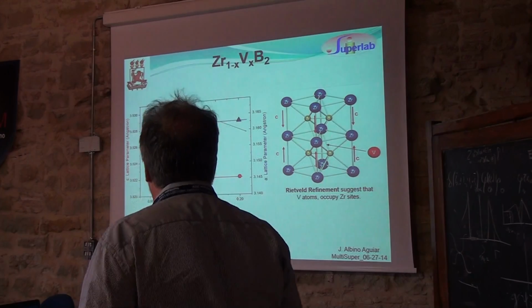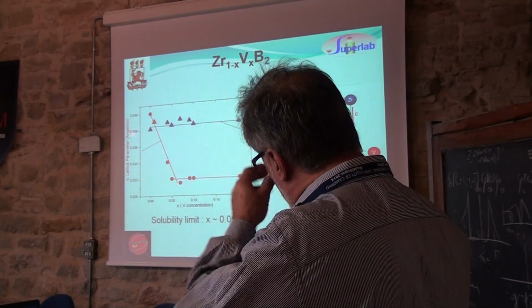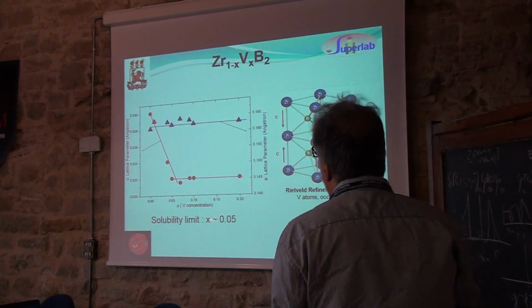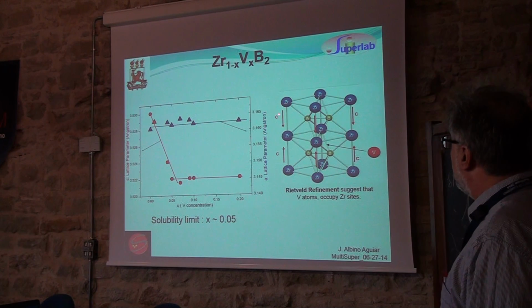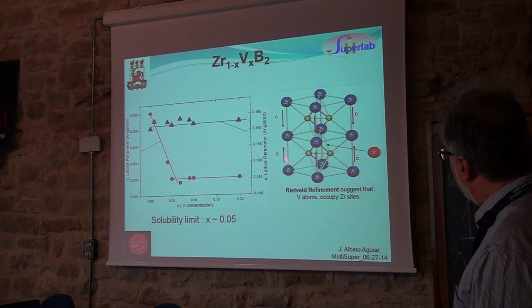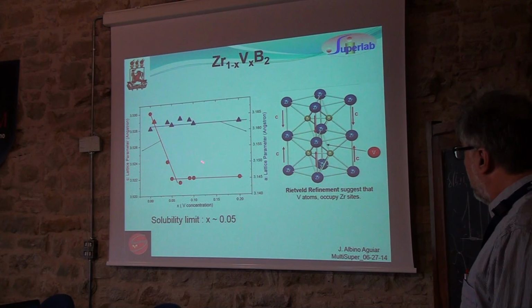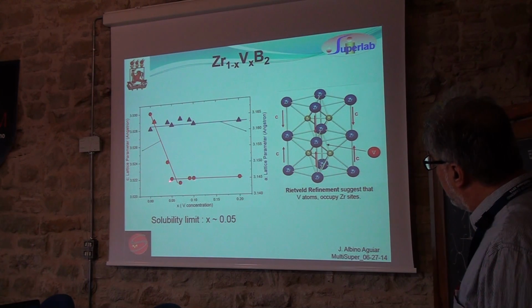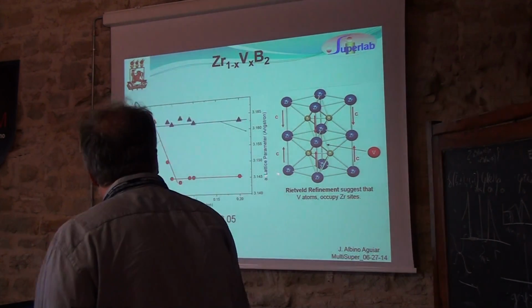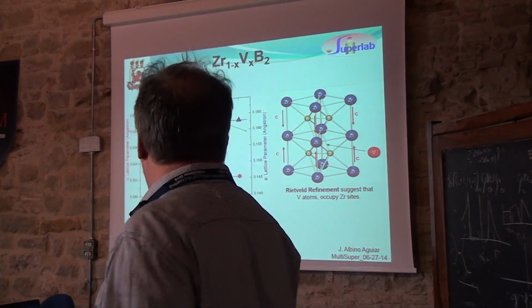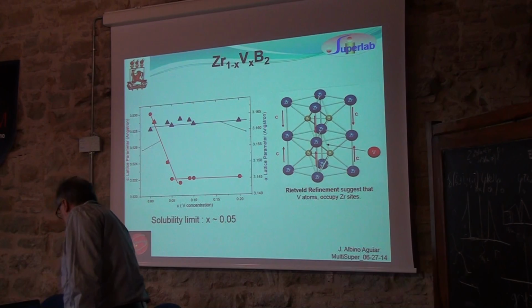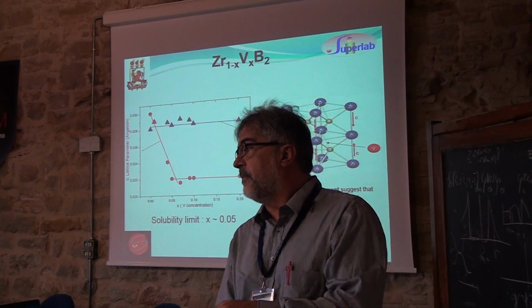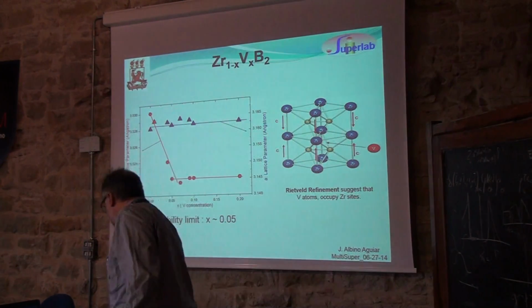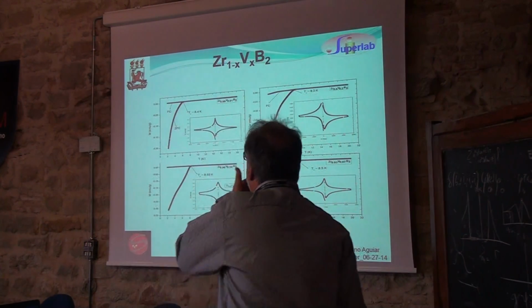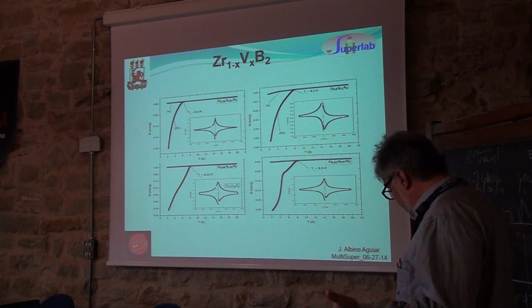Okay? If you draw the lattice parameter as a function of the vanadium concentration, you see that the a parameter is constant with doping, but the c parameter decreases. And then when you reach about 0.05, it is still constant, there is no variation. So this is an indication that we have a solubility limit of 5% in this material. So when you are doping, you are compressing the c axis. So there is a compression of the unit cell. So now that we have structural data, let's look at magnetic data.